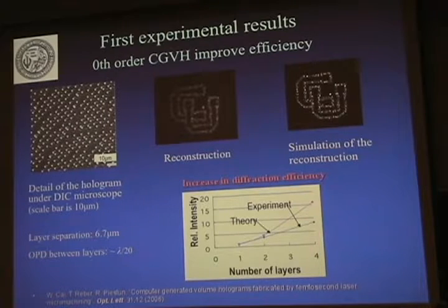So this is the first of such holograms we fabricated. We have a femtosecond laser in our lab, so that's what we use to fabricate this. We took a piece of glass microscope slide, and then by scanning a focused beam, you can modify the refractive index of the glass locally by a nonlinear process. I'm going to talk a bit more about that.